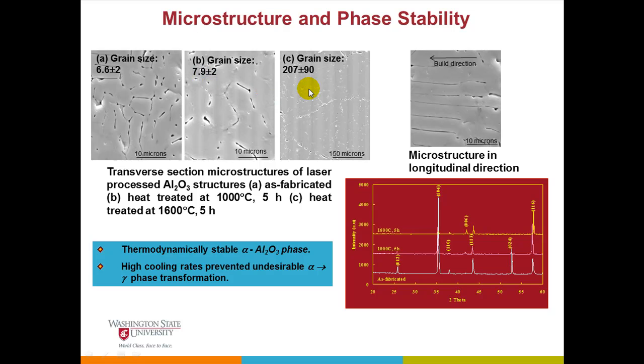By the time you are heat treating at 1600, there's a large difference in grain size. This is the build direction, and you can see the columnar grains in the polished microstructure. These are all alpha alumina, so we are not making any phase transition. These are pure alpha alumina, which is what we are processing using LENS.